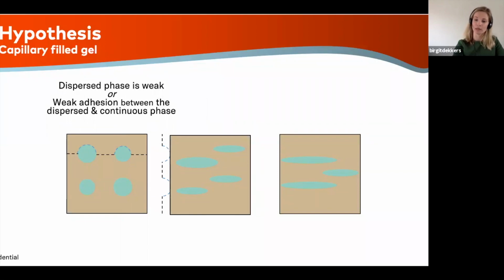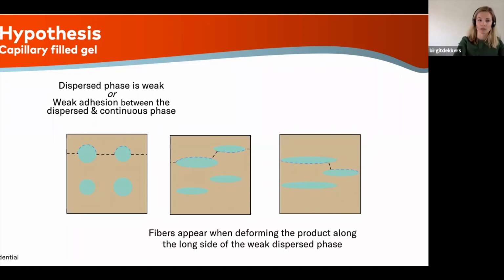Whereas if you are able through our process to deform and align these types of dispersed structures, you see that the weak area is much smaller if you pull apart these structures in parallel to the shear flow direction than perpendicular to it. And the more you're able to deform and align these types of dispersed phases, the larger this difference becomes. And the more pronounced the fibers you get. So we call this a capillary filled gel, where you have anisotropy in your dispersed phase.